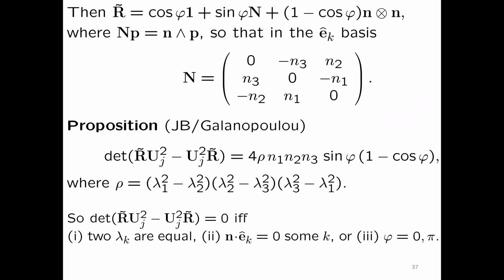Yeah, so what's interesting is that for a cubic to tetragonal transformation, 2 of the lambdas are equal, right? So you can make these interfaces, but of course, if you take a curved grain boundary, then you won't have this holding. So this is a calculation which is just the beginning of trying to understand some of the compatibility issues at grain boundaries.